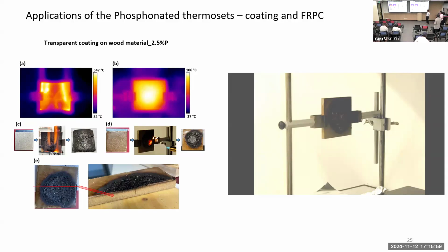Before, when we worked on cotton finishing, to make cotton stable enough, flame retardant enough, the phosphorus needed to be over 3.0%, 3%. So that's for cellulose. But here for wood or for the coating, you really don't need that much phosphorus, and it can resist continuous burning. Then for the testing, how long can it be stable? If we continuously apply the flame on the surface, 10 minutes, 20 minutes, then finally it may be consumed or not consumed. I think it's a good question, but these 5 minutes of flame exposure already is quite long for us.